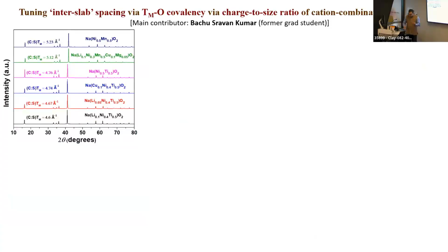So to test the first hypothesis, that by lowering the charge to size ratio of my cation combination in my transition metal layer, so this is what I mean by my cation combination in my transition metal layer, can I improve the air-water stability? Based on my hypothesis, the cathode material bearing the lowest charge to size ratio should give me the best air-water stability, and this should be the worst of the lot.